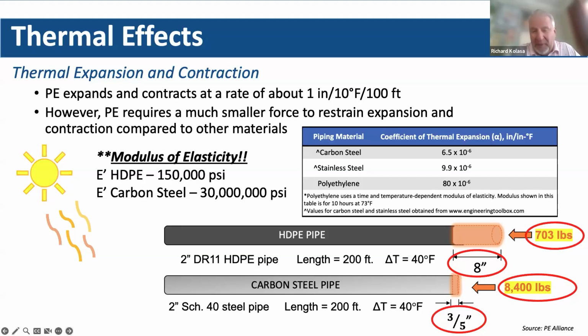We're saying no. From experience and what we see in the ground, if your total system is polyethylene, where all the joints and fusions and everything are self-restrained, we don't see that movement at all. And there was a specific example, I think it was in Minnesota, where they were calculating a 24-inch line that had open vaults with valves in these open vaults. And they were concerned that because the length between the vaults was quite significant, they calculated the thermal expansion and contraction of this line as being fairly significant. And they were worried about the polyethylene pulling out of the valves in those areas.